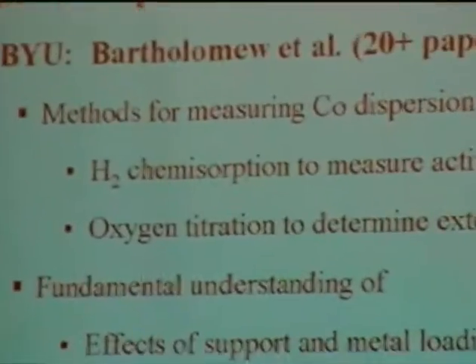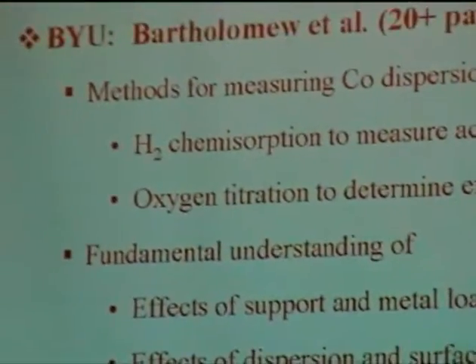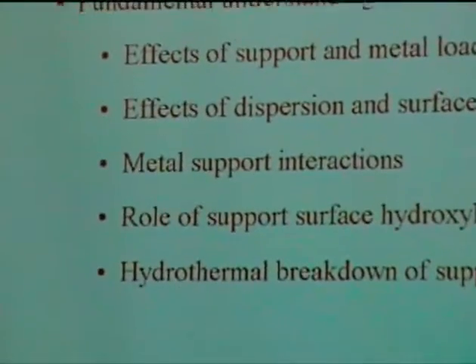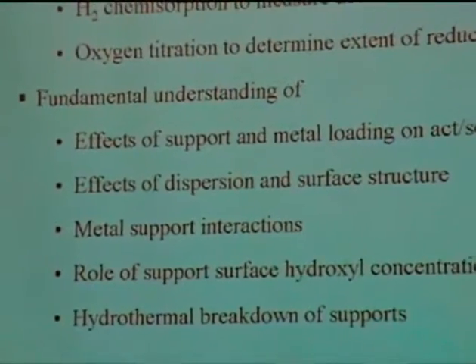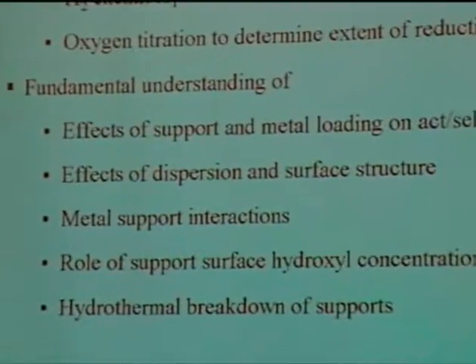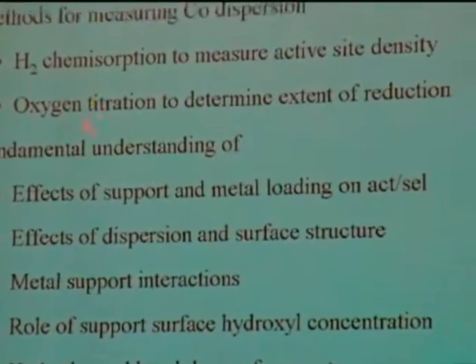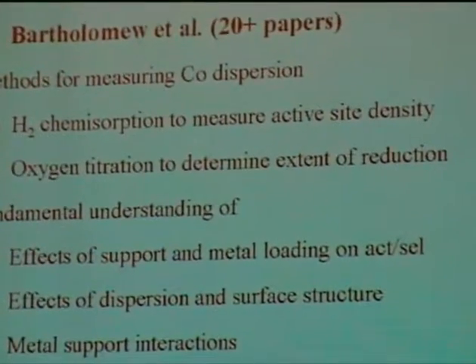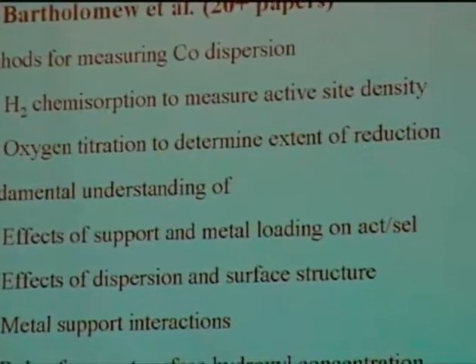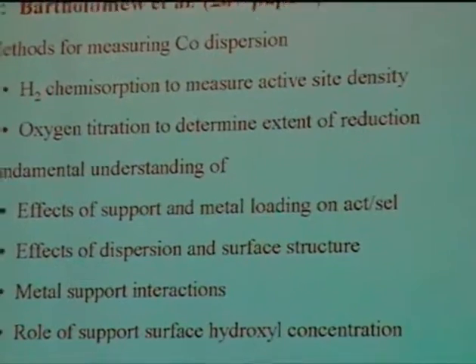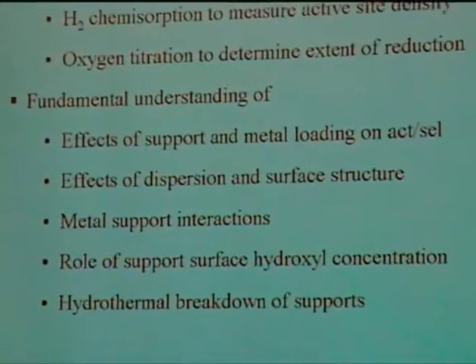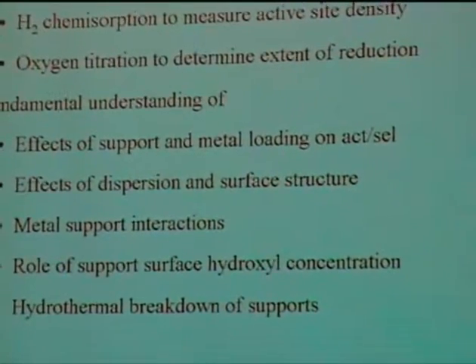In our laboratory at BYU, I had a number of students work with me on many different aspects of cobalt catalysis over a period of about 15 years, starting in about 1976 or so. And we developed methods for measuring cobalt dispersion, hydrogen chemisorption to measure active site density, and oxygen titration to measure the extent of reduction. I think these have become standard techniques now for catalyst characterization of cobalt catalysts.